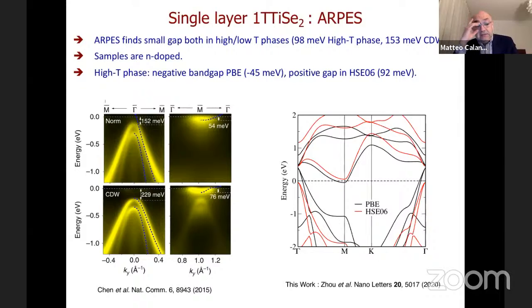And this has been studied substantially by several workers, including me in previous works. The same problem occurs in the bulk. Density functional theory with semi-local functionals tends to overestimate the band overlap between the titanium D bands and the selenium bands. However, this can be solved in two ways. One is doing HSE06. If you do HSE06, you obtain results that are very similar to the self-consistent GW.